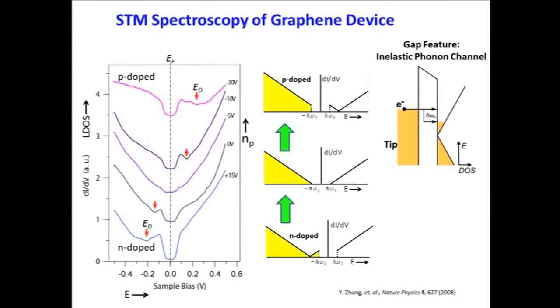And the idea is that when we come to a bias here at about 65 millivolts, then the tunneling electrons have enough energy to create a phonon, an out-of-plane phonon in the graphene, and so that creation of that phonon helps to get the electrons in. So you get a big jump in the current due to this inelastic tunneling channel.